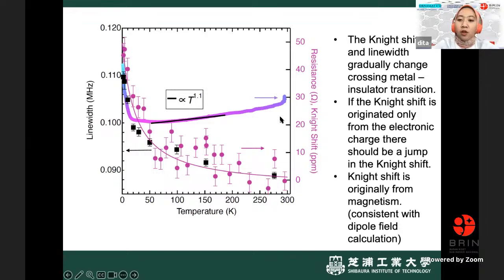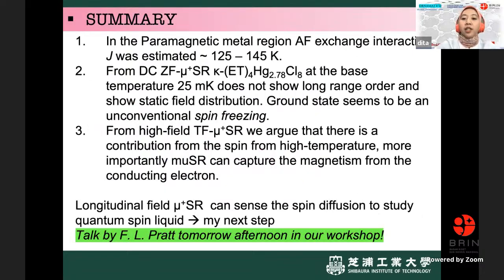Okay, I also plot the line widths and the Knight shift, the line width of the spectra. The Knight shift and line widths gradually change, crossing the metal-insulator transitions. If the Knight shift originated only from the electron charge, there should be a jump because we have a metal-insulator transition, but there is not. It's like a gradual change. So maybe the Knight shift originates from the magnetism of the conducting electrons. So this is consistent with the dipole field calculations.